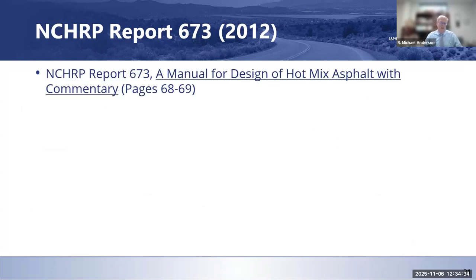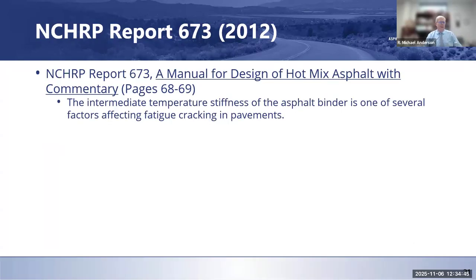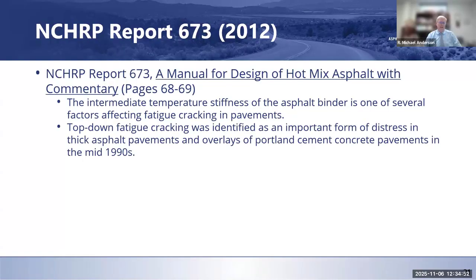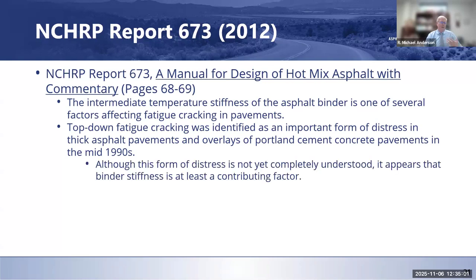This is in 2023 or 2012. This came from NCHRP 9-33, which looked at mixed design and a commentary on how you make changes. And what they noted was that intermediate temperature stiffness of the binder is one of several factors affecting fatigue cracking. We've talked about that. They did say top-down cracking was an important distress, not just the bottom-up fatigue cracking, particularly as you looked at overlays and things that we saw and in thicker pavements.